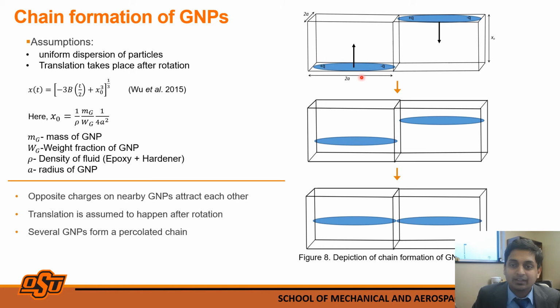After the particles are aligned, they tend to attract towards each other because of the charge formation plus Q and minus Q. So as time passes by, these two particles come closer together and form chains, as shown in figure 8. Wu also found a formulation which tells us about the distance between two particles and the time it takes to achieve the chain formation.